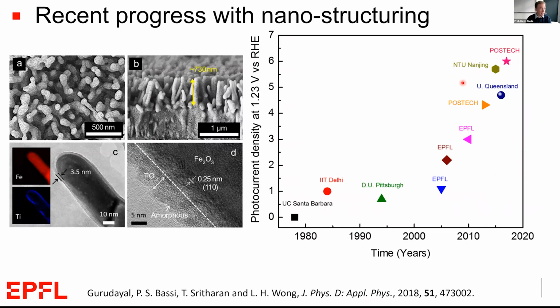Now, many groups around the world, including in Korea, have looked at optimizing this material and have done very well, getting now about 6 milliamps per centimeter squared under the best conditions. But it's extremely difficult to engineer hematite more to get any more current out of it. It's a very challenging material. However, its stability under the water oxidation conditions is an advantage. And perhaps with further work, groups can find ways to further increase the photopotential and the photocurrent on this material.